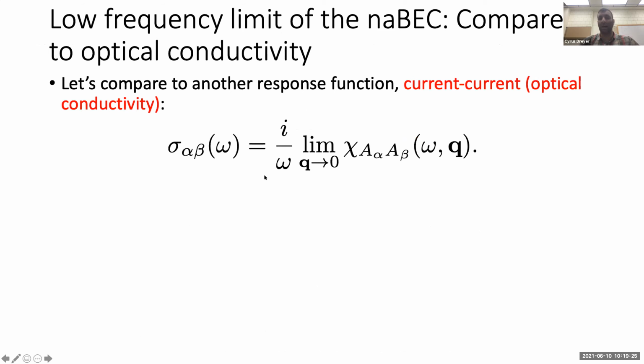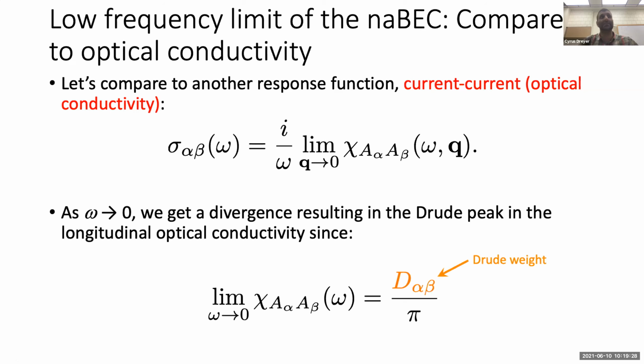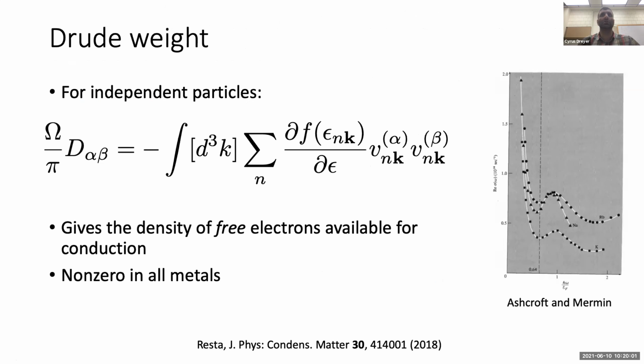What we know about the optical conductivity is that if we take the frequency to zero limit, we get a divergence. This divergence gives the Drude peak in the longitudinal optical conductivity. The reason there's a divergence is that if we take the omega goes to zero limit of this susceptibility, we get a constant, known as the Drude weight. And if we get a constant here, we get a divergence as 1 over omega. A little bit more about the Drude weight, because as you probably could tell from the title, it will feature more prominently in this talk.